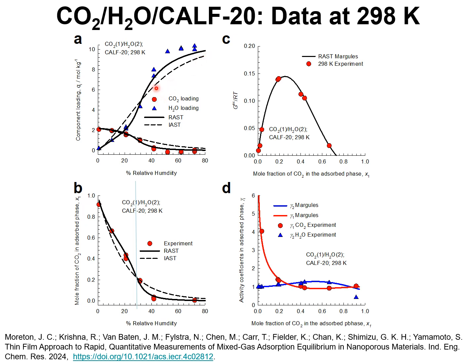Another way to demonstrate the deviations of the experimental data from the IAST is to plot the mole fraction of CO2 in the adsorbed phase on the y-axis as a function of percentage relative humidity. For values of percentage relative humidity lower than about 30%, the adsorbed phase is richer in CO2, i.e. poorer in water than anticipated by the IAST. On the other hand, for relative humidities in excess of 30%, the adsorbed phase is significantly poorer in CO2, i.e. richer in water than anticipated by the IAST.